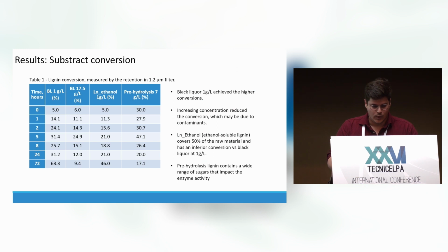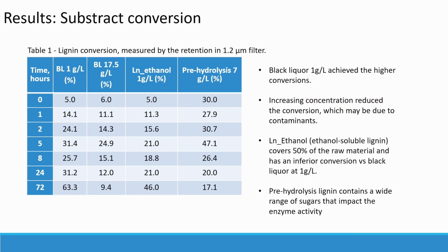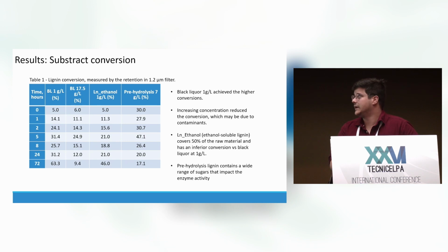So we have decided to go for this lignin. The next step was to evaluate how the different substrates interact with the enzyme. So we studied what we call the black liquor, from the soda extraction, at different concentrations, 1 gram of lignin per liter and a higher concentration. We also studied the fraction that is soluble in ethanol, and we also studied the PREHYDROLYSIS lignin, which is different.